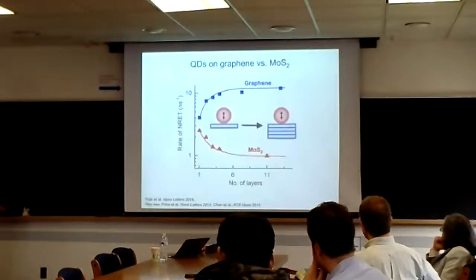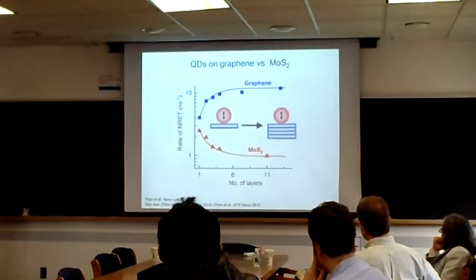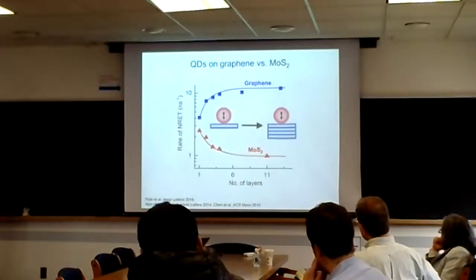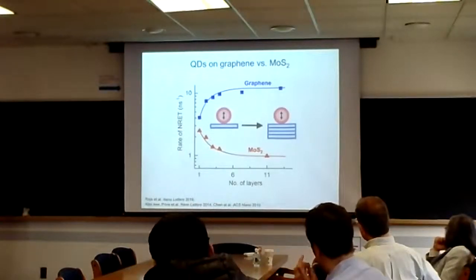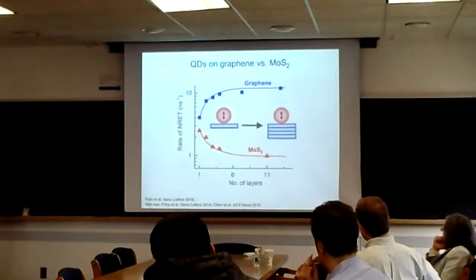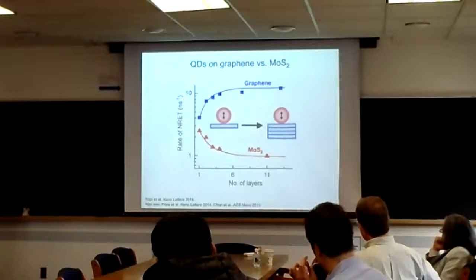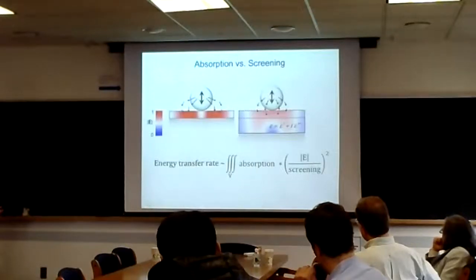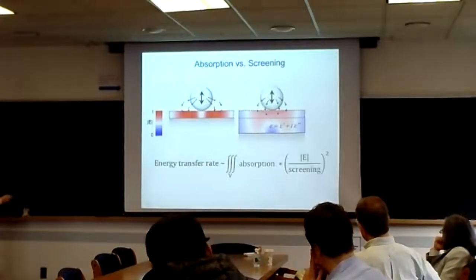This is just a guide to the eye, but we plot the data points here. Even at the monolayer limit, graphene is more efficient at this energy transfer than MoS2. And as you start increasing the number of layers, they show completely opposite trends. This went against our intuition at the start. So before I show the comparison with the theory, I wanted to motivate the physical picture here.